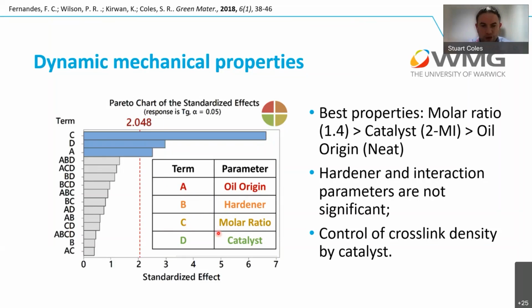The catalyst was shown to be significant. The 2-methylimidazole worked much better than the triethylamine. We were getting much more significant increases in properties with that catalyst to start with. Solubility issues, steric hindrance, and electronics all play into this area. And then you've got the oil origin as the last factor. Effectively, if you use neat oil, you were getting a significantly better material than if you used the waste oil.